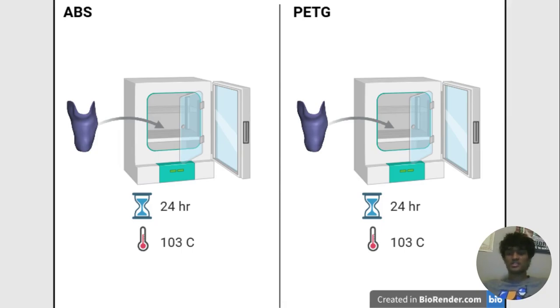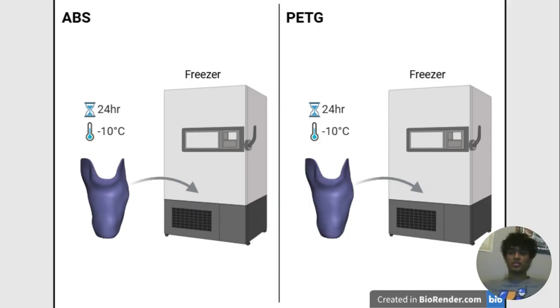The first test conducted was a thermal resistance test in the warm variant. This test revolved around placing each prosthetic in an incubator for 24 hours at 103 Celsius to examine the hardness values before and after. The same test was conducted in the cold variant, where each prosthetic was placed in a freezer for 24 hours at -10 Celsius degrees to see how exactly the cold temperatures affected the hardness values.